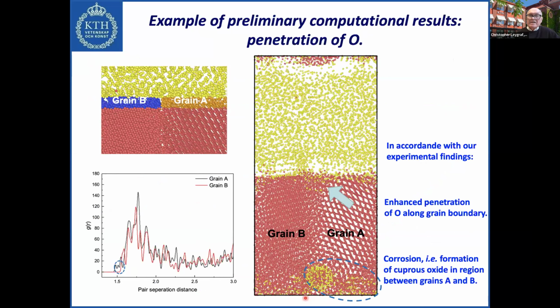Here we see the penetration of oxygen. You can recognize here, this is grain B, this is grain A, these are the corrosion products. But we can also see how this oxygen can go deeper into the material and along the grain boundaries. So there is really also seen here a penetration of oxygen along the grain boundaries.